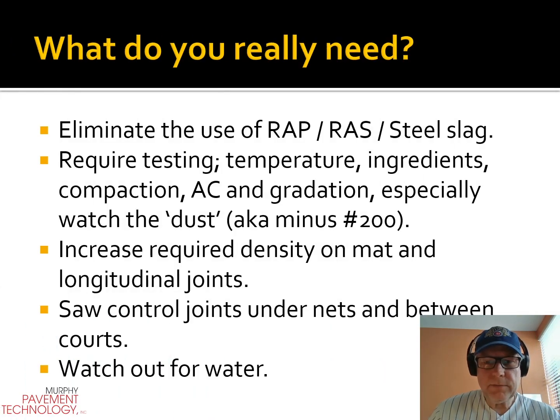Eliminate the use of RAP, shingles, and steel slag on surface courses in particular. Require testing, quality control and quality assurance both: temperature, what are the ingredients, asphalt content and gradation. Watch the 200, and definitely have a density technician checking the mat and joint densities in the field. Saw cut control joints under nets and between courts if you think it's appropriate, and watch out for water.